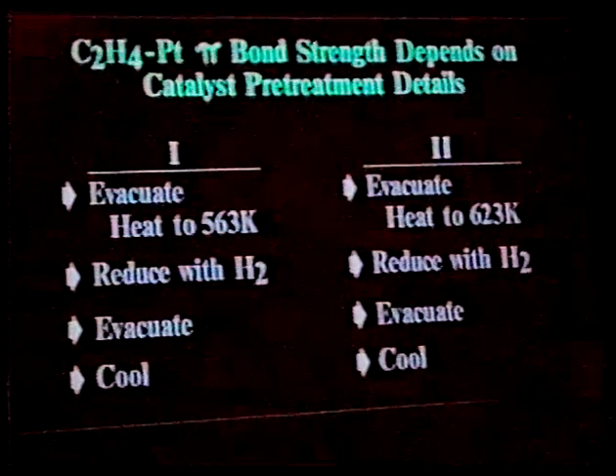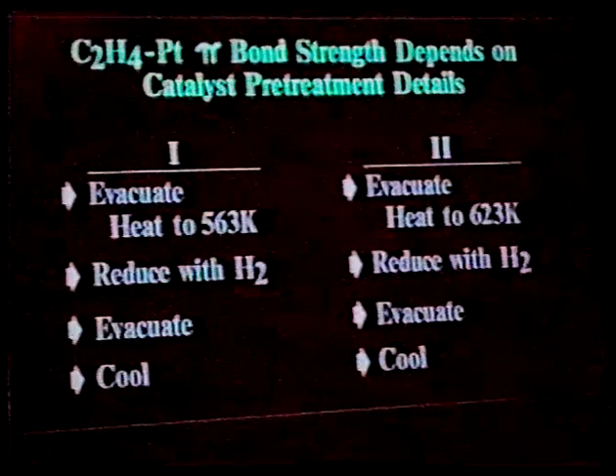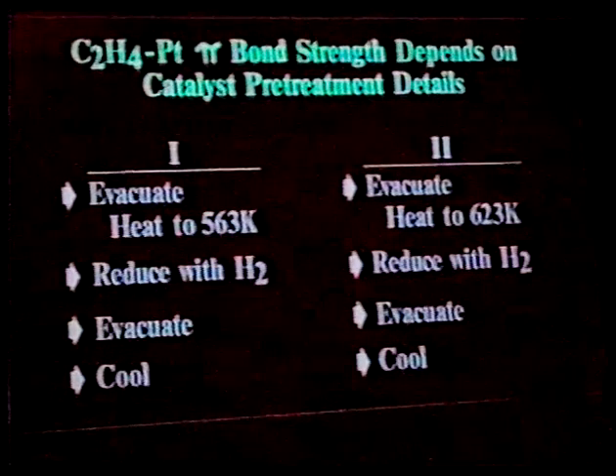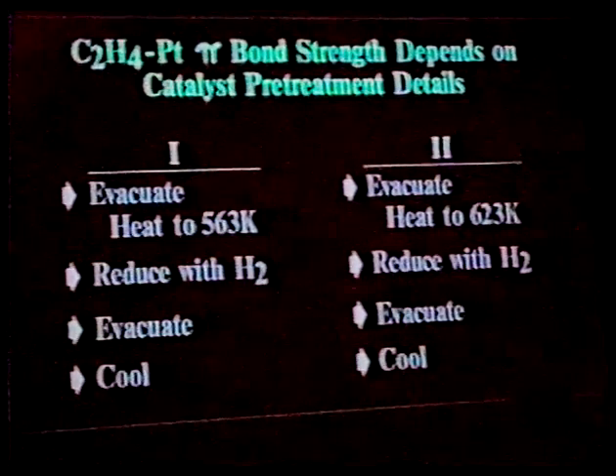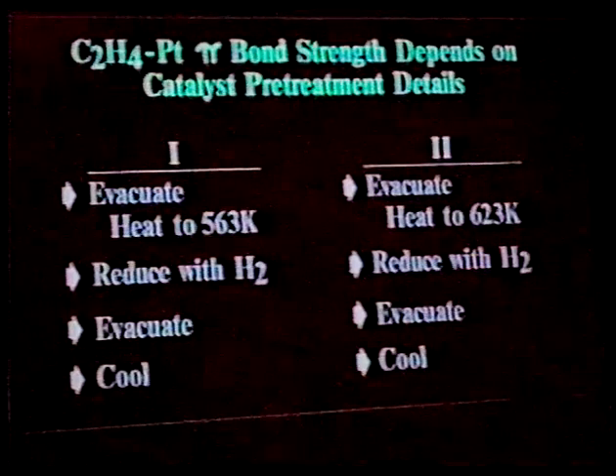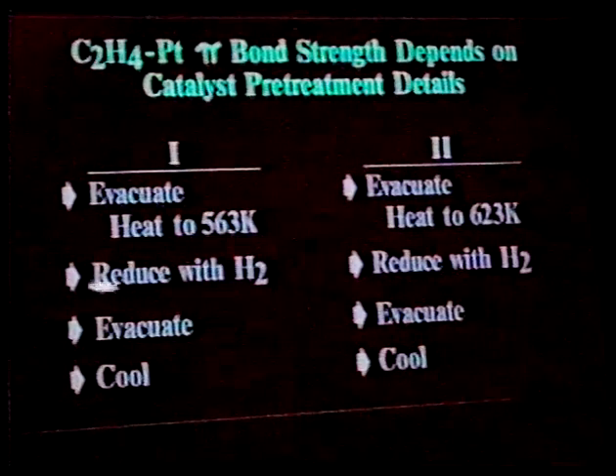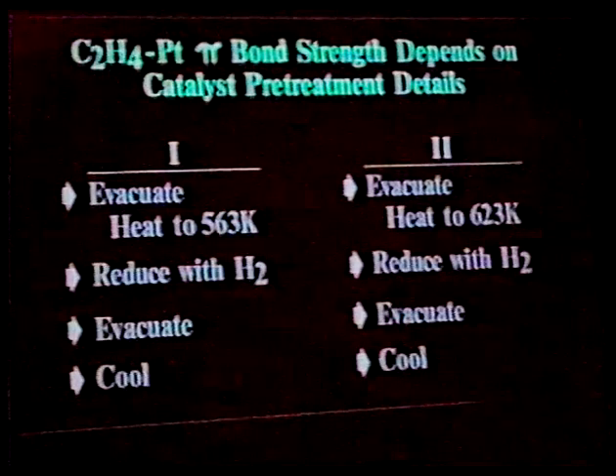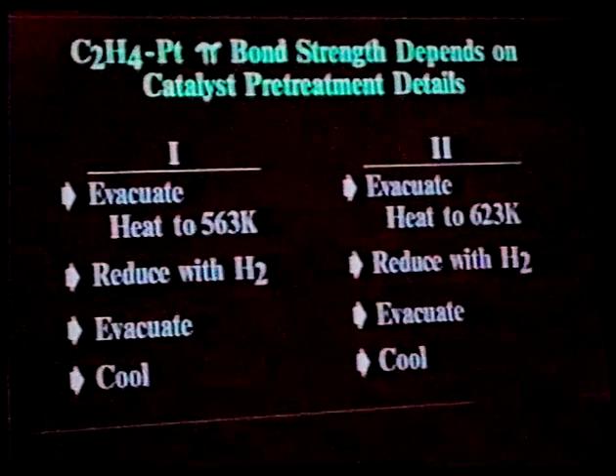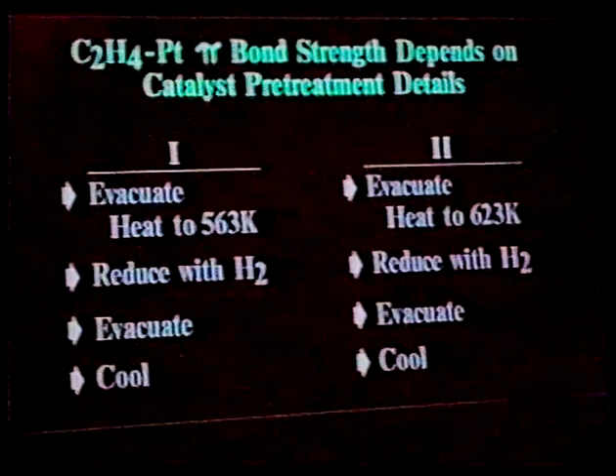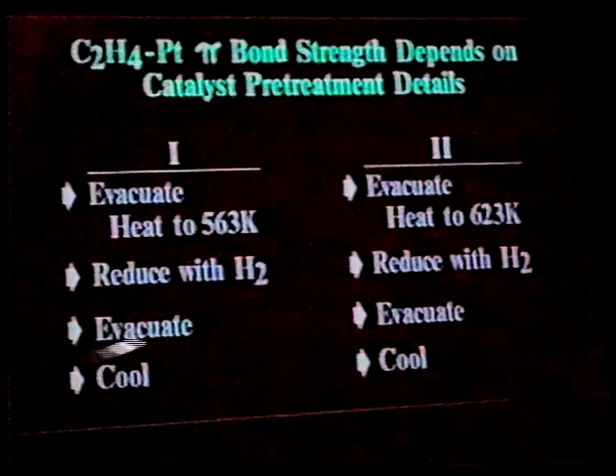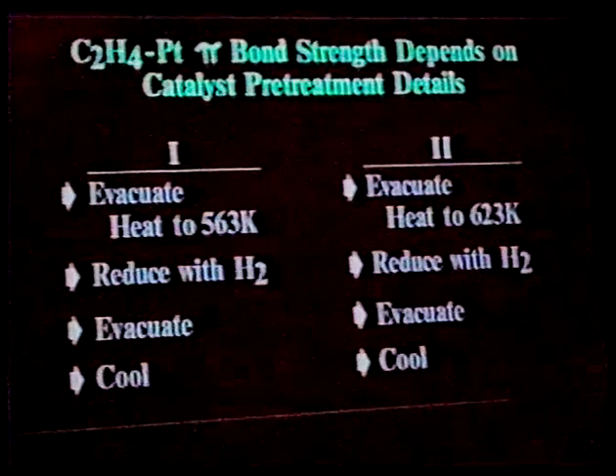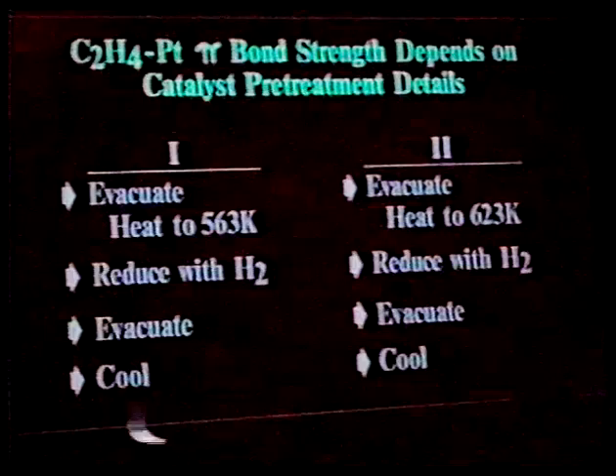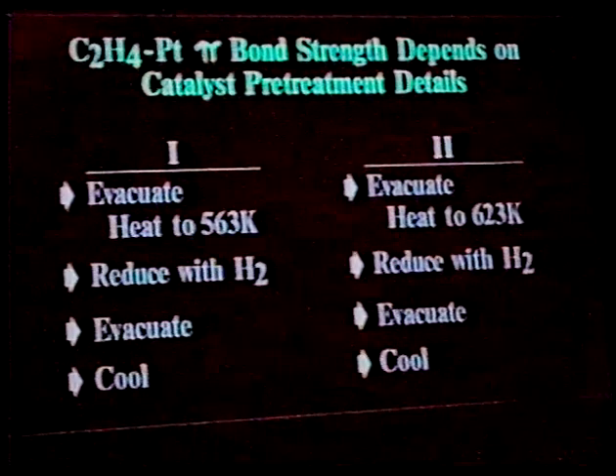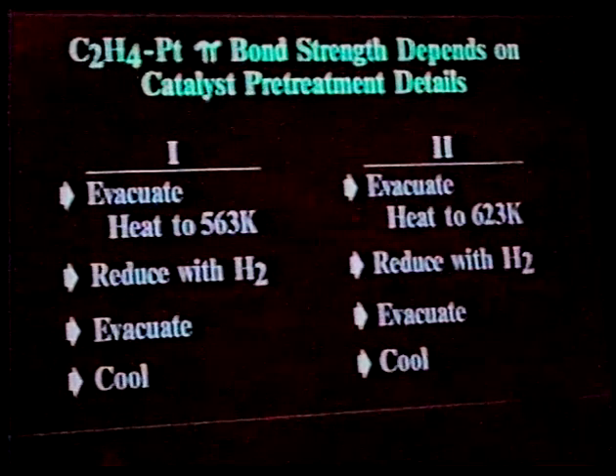And in one case, we would heat to 563 Kelvin. 563 is about the range of temperatures that have been used previously in activating these kinds of catalysts. We saw no real reason to go at any higher temperature. So we then expose it to H2 in a static case. We can vary the pressure between 10 torr and 400 torr. It doesn't seem to make a whole lot of difference. You then evacuate for about half an hour under those conditions, cool the sample down to whatever temperature you'd like, absorb the ethylene and see what happens.